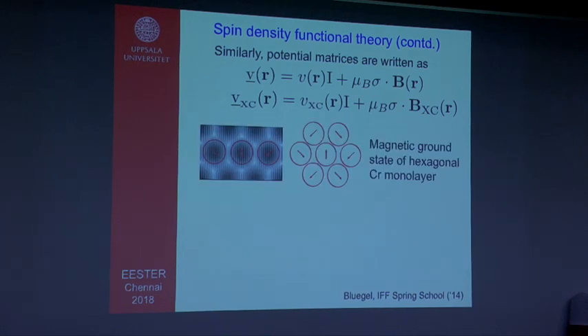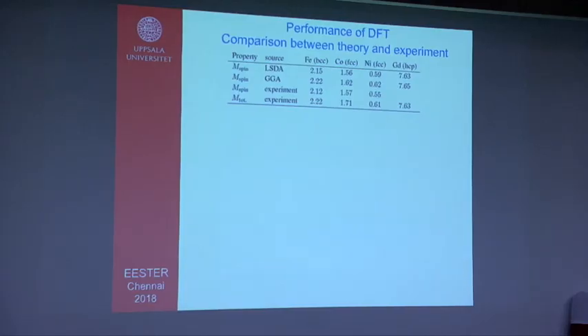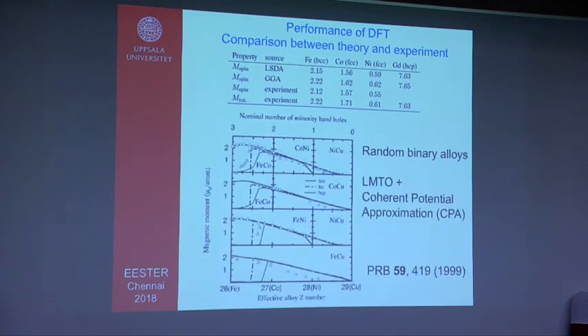So this is a typical picture that you can generate. This is the magnetic ground state of a hexagonal chromium monolayer. This is a full potential calculation where you see the magnetization density. Most probably you cannot see it from a distance, but they have a very nice agreement with each other. I would say it's a very good agreement between the spin moments, between theory and experiment. That gives us a lot of confidence that we can use spin density functional theory. I can show you more.